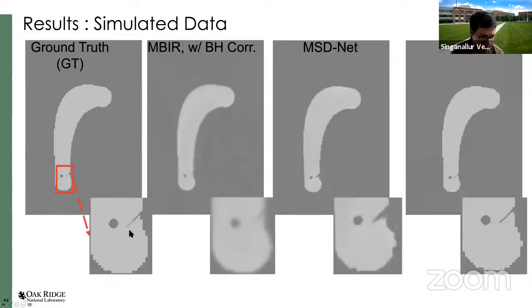And if I zoom in a little bit and start looking at some of the cracks, we see some blurring, but we also believe that maybe we need to adjust the parameters a little bit for these model-based methods, regularizing-wise. But both the mixed-scale DenseNet, which is based on dilated convolutions, and the patch-based neural network do a pretty good job. In this case, we actually observed that neural networks trained with smaller patches were able to resolve some of the tiny features better.